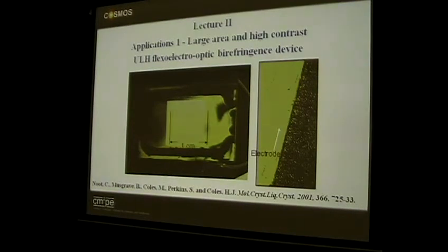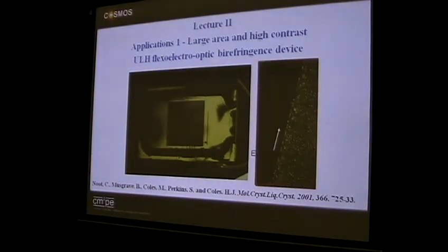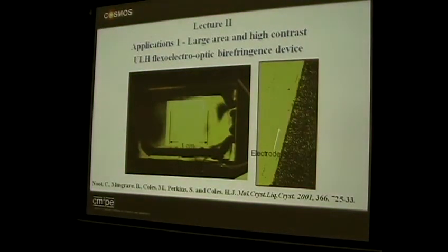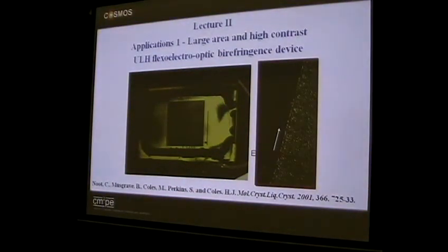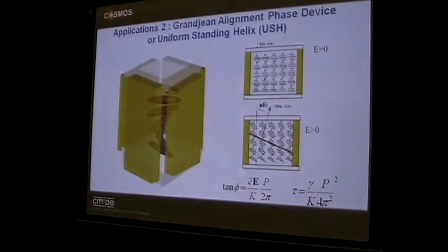And you'll see that as I apply a field, it switches from one state, the bright state, to the dark state. Normally you'd set your device to be dark with one polarization of light, and then switch back to the bright state. And there's a very good optical contrast. And that's the basis of the flexo-electro-optic display devices in the so-called uniform lying helix. There is a second device that we started to make. We made it for a telecommunications application where people wanted to make phase compensators. And we had a four electrode array.